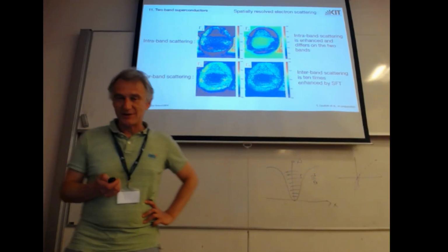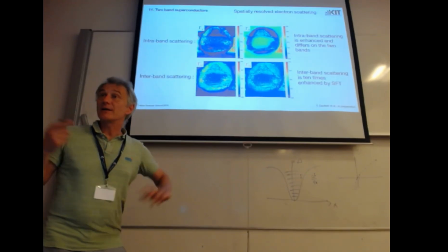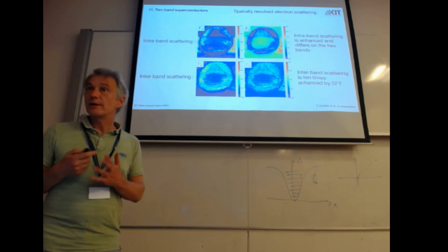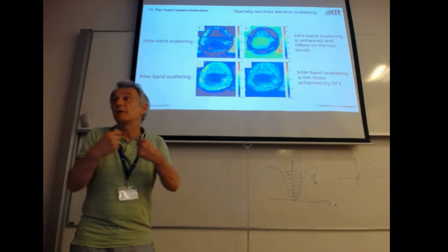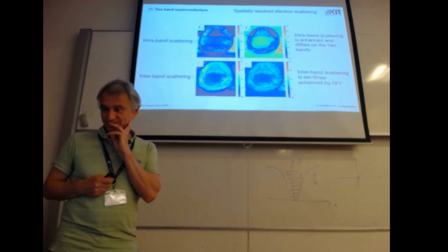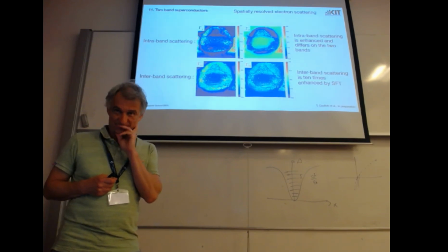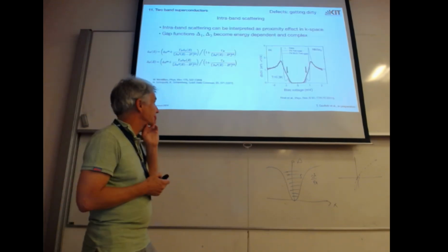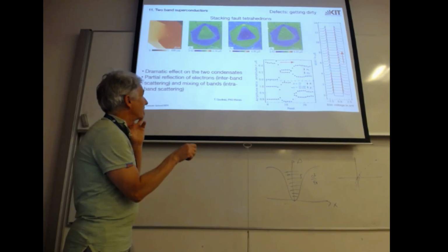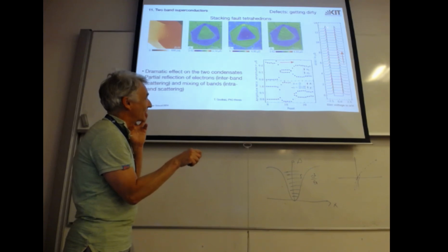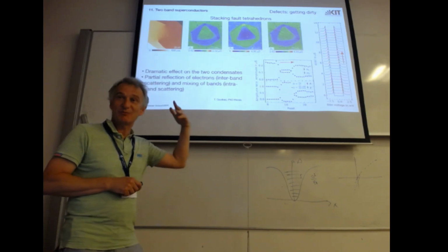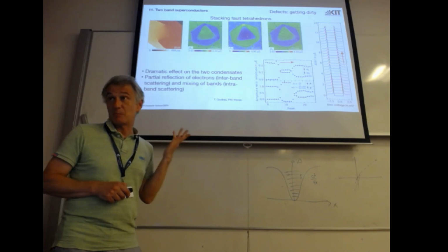So I think we understood this data: the bands are not coupled, but if we have defects, we will couple the bands, and then two order parameters will merge and make a shift in energy. And do I understand correctly that if I go away from this defect and scan the spectrum somewhere away, I'll restore the picture with two order parameters? Yes. Far away here, this spectrum is very tiny, but it's a normal spectrum, the conventional spectrum of the two-band superconductor with practically no coupling.